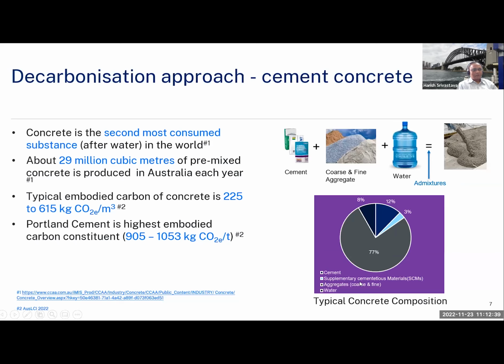But if we look at the picture on the bottom, cement is about 12% in a typical mix, whereas aggregate is about 77%. And if we come back to the left-hand side, out of the total embodied carbon of anything from 200 to 600 kg per cubic meter, about 900 to 1000 kg per tonne embodied carbon is attributed to cement.